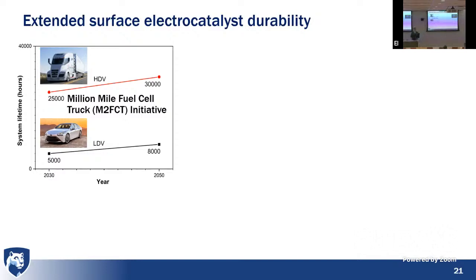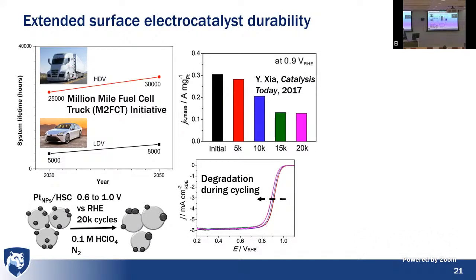And so one of DOE's targets is to get system lifetimes of 25,000 to 30,000 hours. For the fuel cell here, I think we've already offered 6,000 hours stability, so we're sort of here, but going to 25,000 hours stability is a challenge. And so the state-of-the-art catalyst is those platinum nanoparticles on high surface area supports. And if you run an accelerated durability protocol, that's a way of how we determine how stable the materials are. We'll see for this platinum on carbon that these platinum nanoparticles, you'll have oxidation of the metal, you'll get metal ions, you'll have particles coalescing or aggregating together.